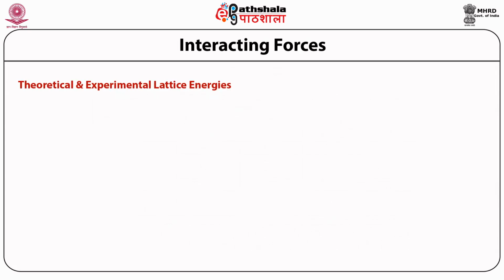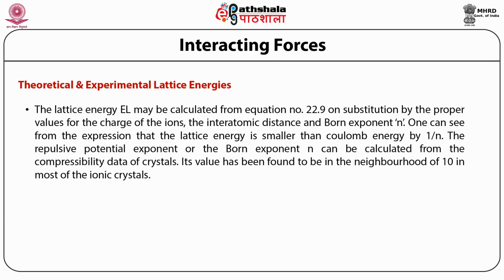Theoretical and experimental lattice energies. The lattice energy E subscript capital L may be calculated from equation number 22.9 on substitution by the proper values for the charge of the ions, the interatomic distance, and Born exponent small n. One can see from the expression that the lattice energy is smaller than Coulomb energy by 1 upon small n. The repulsive potential exponent or the Born exponent small n can be calculated from the compressibility data of crystals. Its value has been found to be in the neighborhood of 10 in most of the ionic crystals.